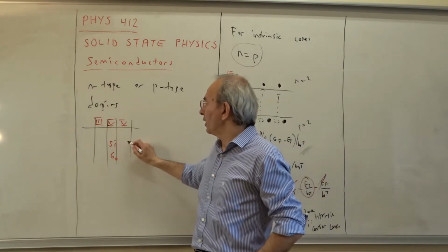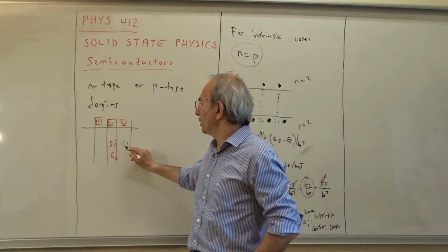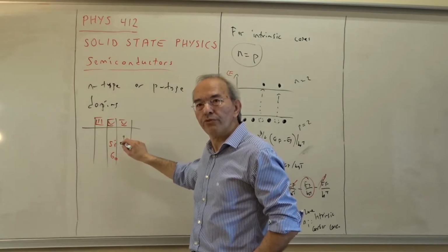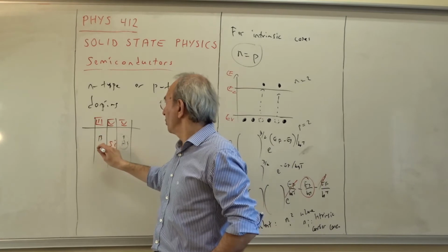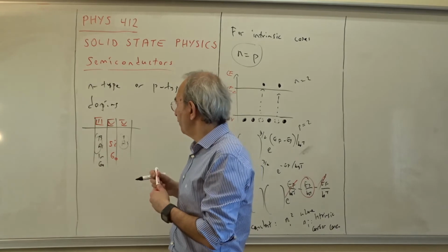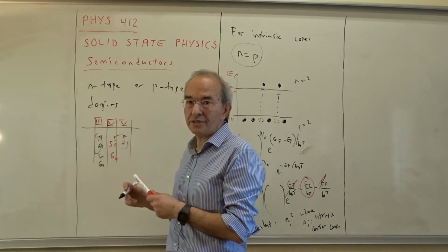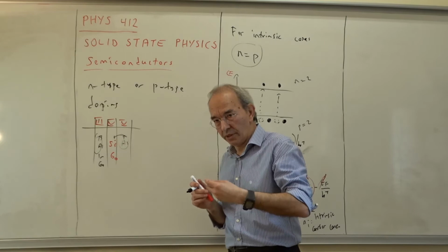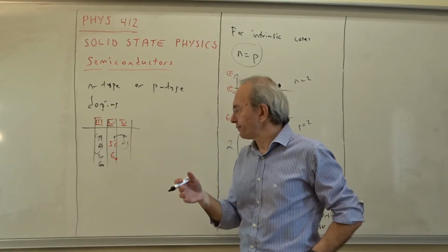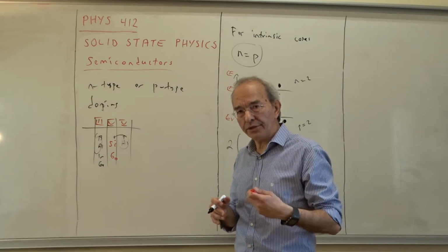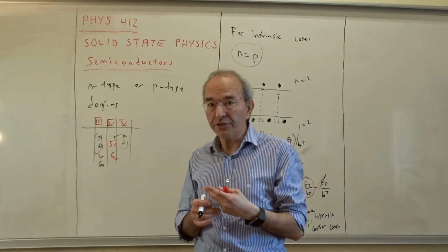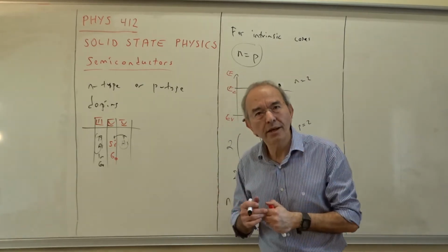And if anything, let's say arsenic, phosphorus, from the group 5, or boron, aluminium, indium, gallium, etc., one of them from 3, if these are on purpose added to the group 4 elements such as silicon or germanium, then we can have a much greater concentration. Much greater concentration means much greater conductivity, as we see in the following example.